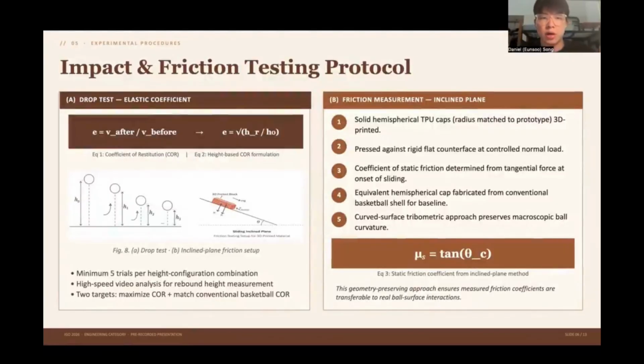Drop tests at four heights capture how TPU stiffness shifts with impact speed. Friction testing uses curved hemispherical specimens rather than flat material, preserving the real contact geometry that governs the grip.